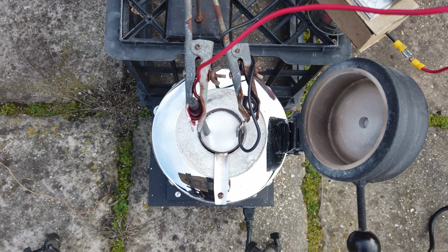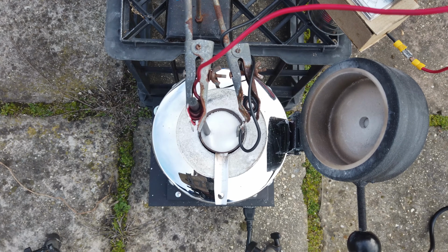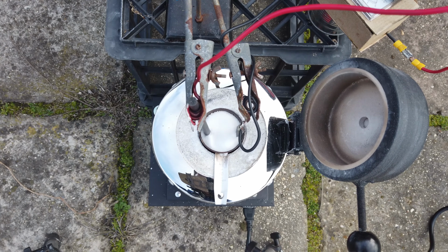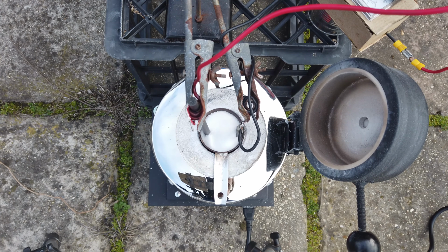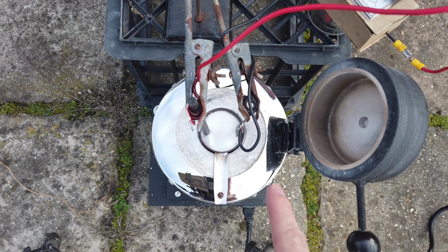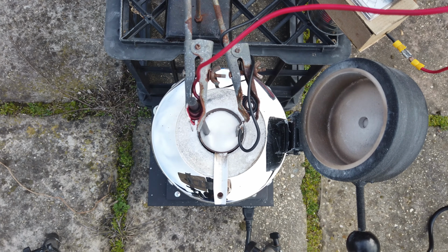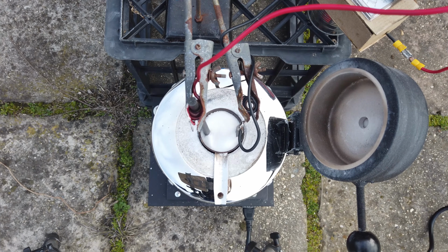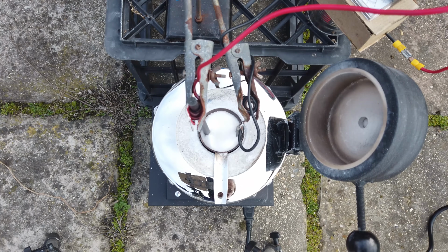Okie dokie, so starting our experiment now, what I've got is our eutectic mixture in a stainless steel measuring cup, slowly heating on the furnace. We have set up already and connected to the power supply a graphite anode to generate chlorine and a nickel cathode to generate our lithium. Of course, we're trying nickel first because we expect it to hopefully give us a slightly purer product, but if things don't go quite as planned, we will be trying out an iron electrode. Anyway, we've just got to wait for our mixture to melt and then we'll turn on the current and see what happens.